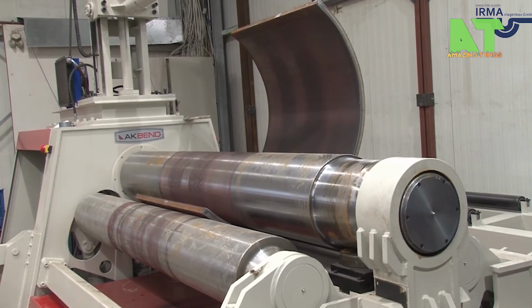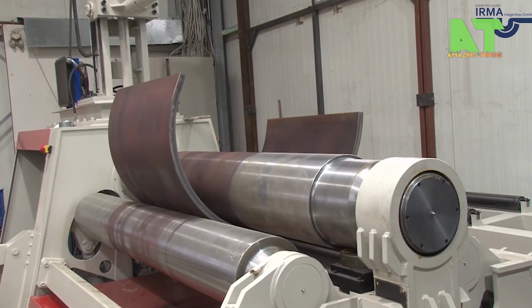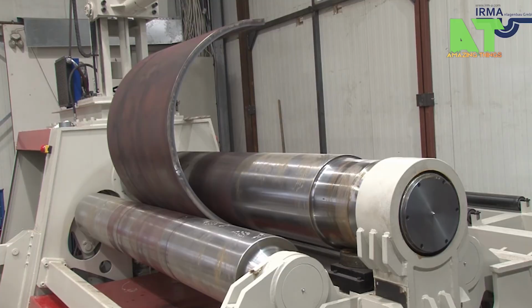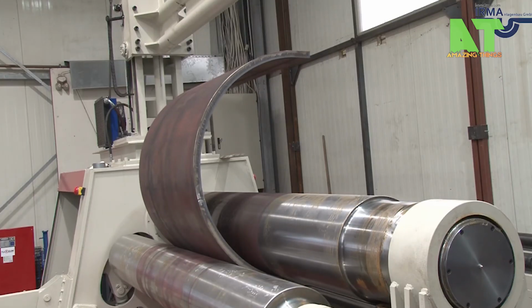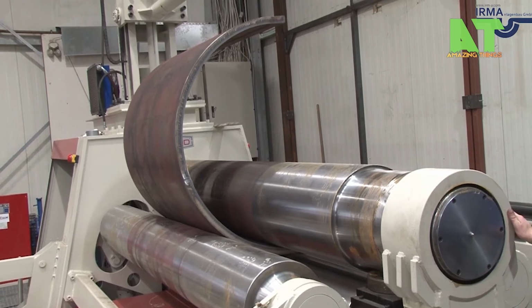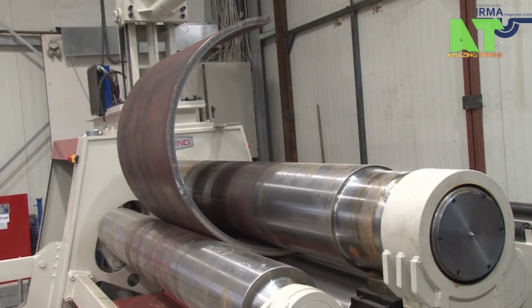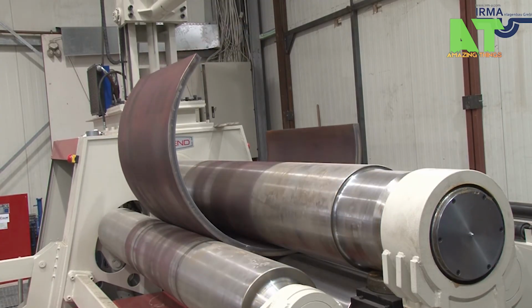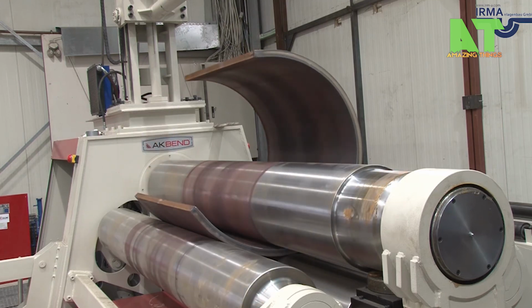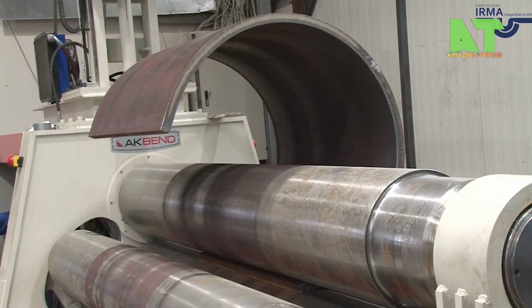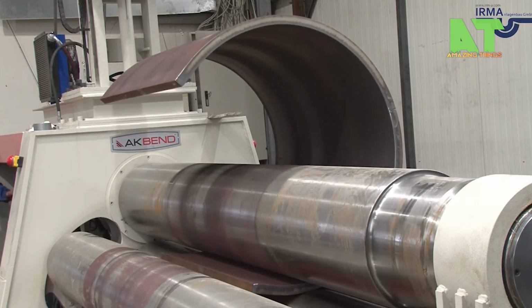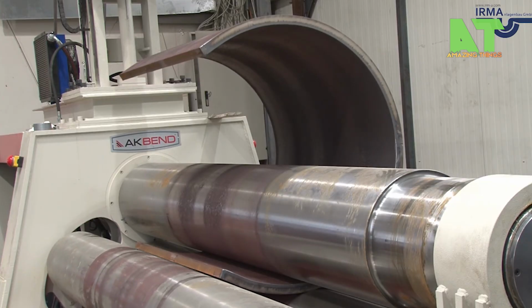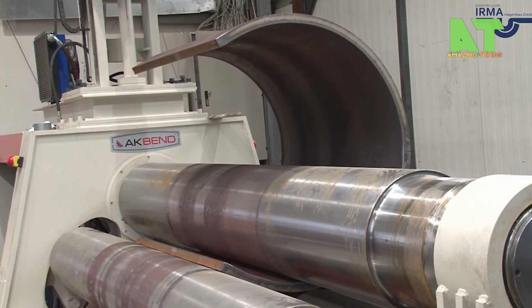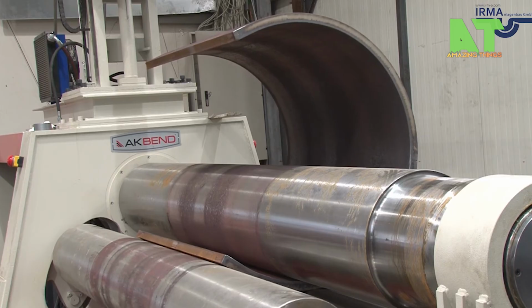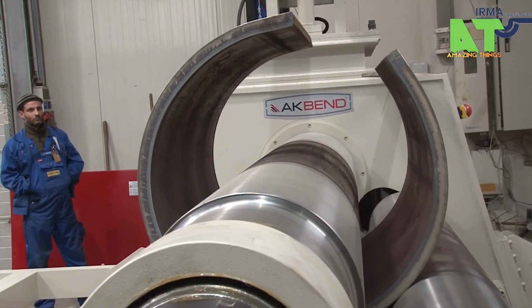The operator, or the CNC system, sets the position of each side roll according to the desired bending radius. The plate then passes through the machine, and as it does, the rolls apply progressive, even pressure across the entire width, curving the metal smoothly without local stress concentrations. One of the AHS 30-45's most impressive features is its pre-bending capability. Traditional plate rolling always leaves straight, unbent sections at each end of the plate, the so-called flat ends, which then have to be pressed separately. The 4-roll design minimizes this problem significantly because the pinch roll grips the plate right at the end, allowing the side roll to begin bending almost immediately. The result is a much more consistent cylinder with minimal flat areas.